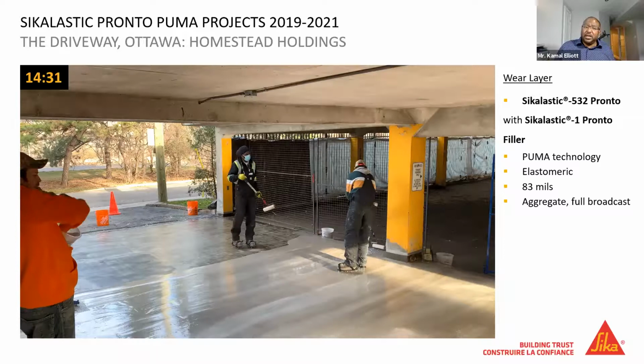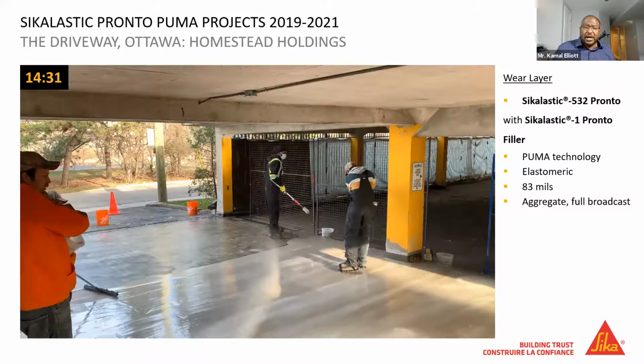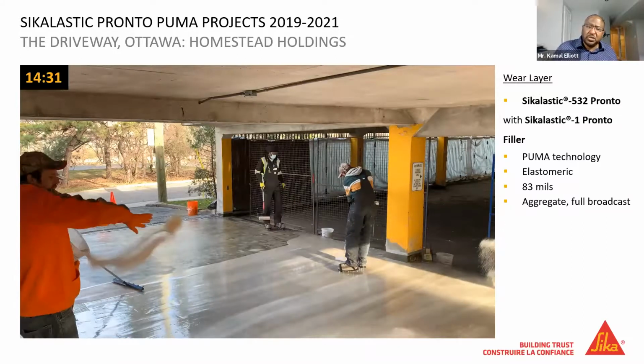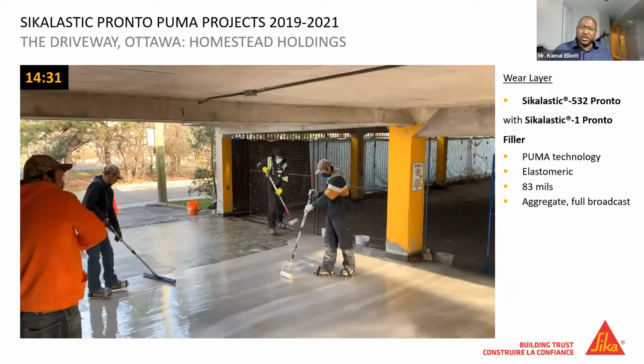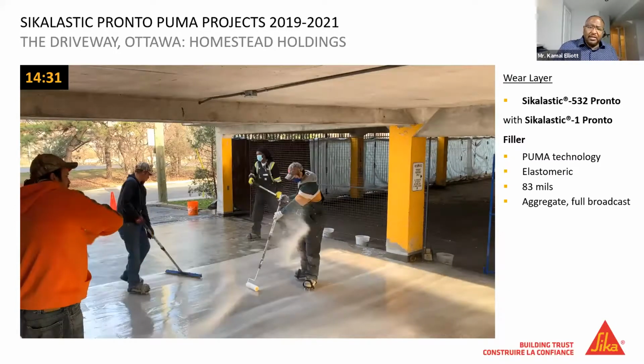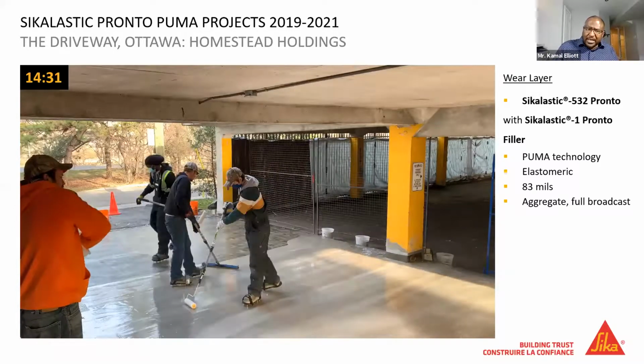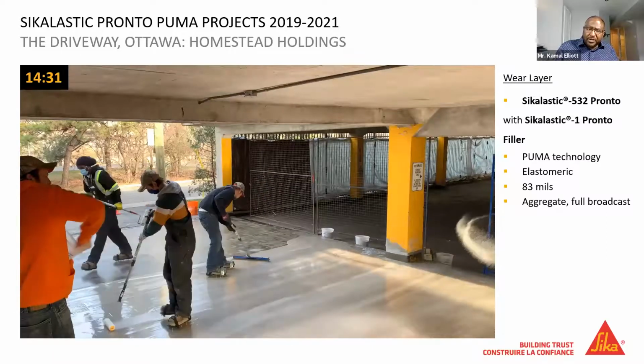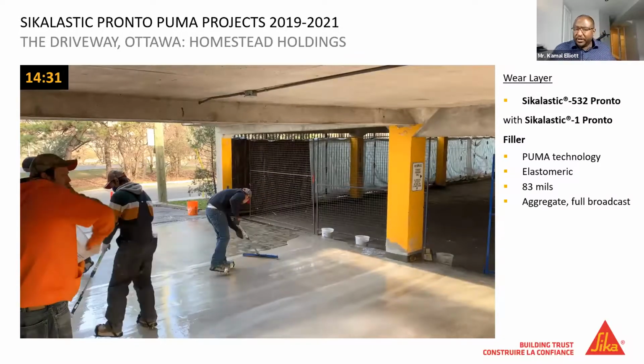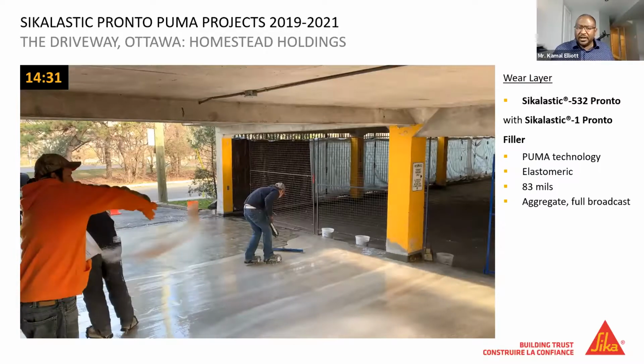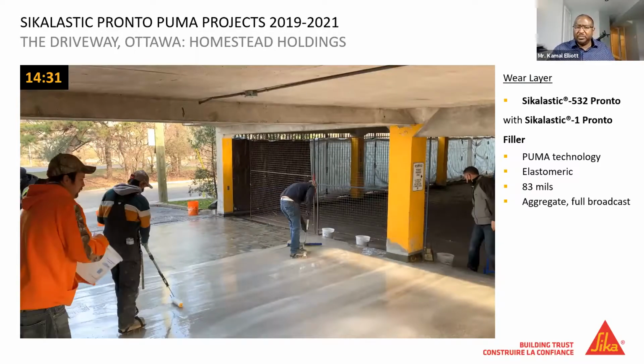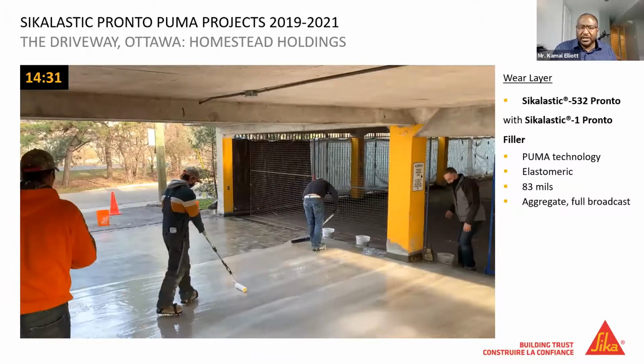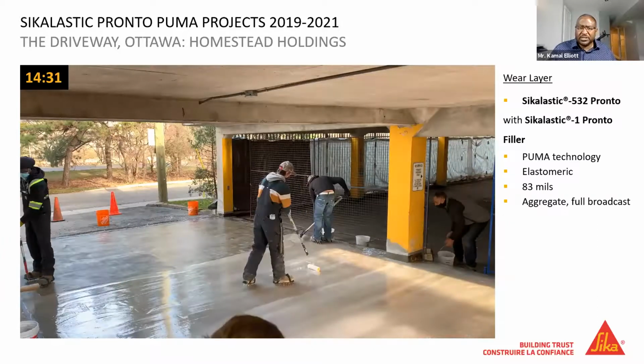So you're seeing here the V-notch squeegee is being used to spread the material. There's again the spike roller to make sure there's no air. And then we have our friends broadcasting into the aggregate, and they're essentially going to carpet that whole area. So there won't be any wet appearance left. It'll be completely carpeted with aggregate, silica quartz in this case.